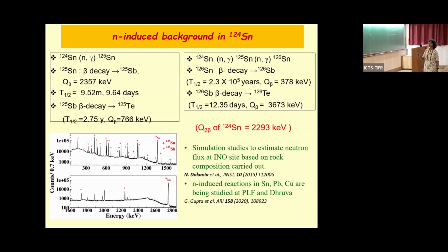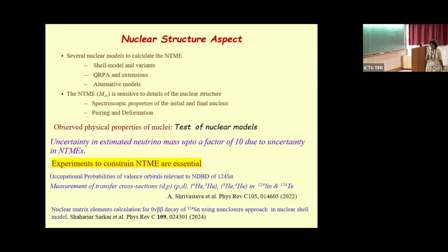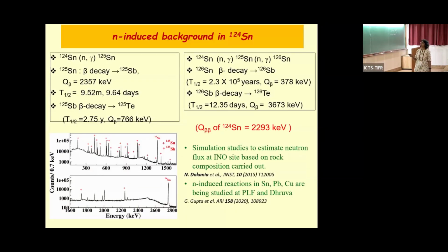Now 126 tin has a beta decay Q value of 378 keV, but has a long half-life if it goes to 126 antimony. But 126 antimony has a very high Q value. Again, so in 10 power 5 years, it will become a significant background from the enriched 124 tin. So this is a concern, and we had to understand this. So some studies were done with different neutron capture measurements, both in accelerated neutron beams and in reactors. So the only thing in this case is that you have to minimize the exposure to neutrons. So store them underground, also surrounded with hydrogenous material which will absorb neutrons.